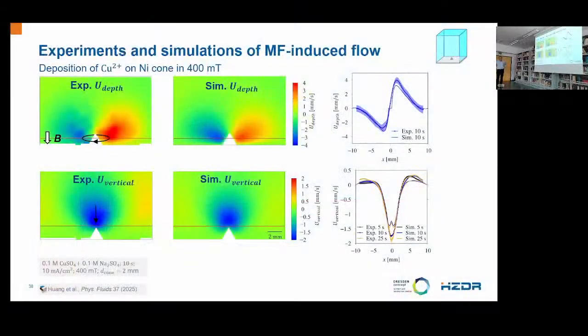Thank you for the question. Actually, this also confused us, and our possible explanation is that in the experiment, the lowest point of the coordinate is determined by the lowest particle that can reach inside the fluid. It might actually not be the real lowest point of the cell. So we see that here we have a very high gradient of the flow, so it increases from 0 in a very short distance to a large value. And we thought maybe there's a small shift in the vertical coordinate system, so that these 2 points have a difference in the velocity.